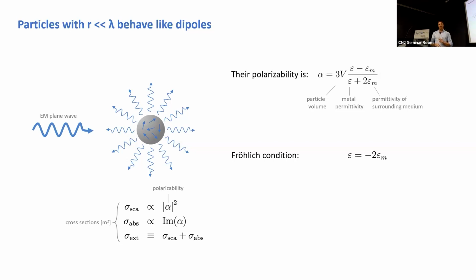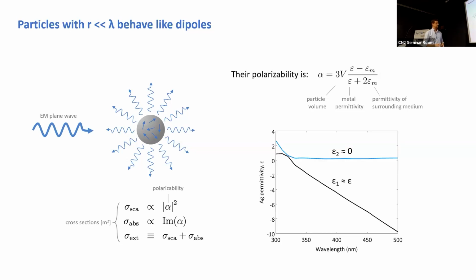Now let's take one metal, the typical plasmonic metal that we like a lot, which is silver. This is the silver permittivity. As I said, there is a real component and an imaginary component. For wavelengths between 300 and 500 nanometers, so let's say UV to the green, the imaginary component, which tells us something about the losses in the material, can be neglected. And so the permittivity of silver is just the real component. And then if you look at where that real component is -2, you will see that that happens around 350 nanometers. And now in the next slide, I'll plot the extinction cross-section spectrum for a silver nanoparticle, and it looks something like this.